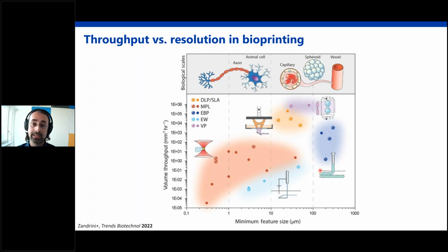And specifically, we developed together with partners in Lausanne a new bioprinting approach that has now been around for a few years since we first published it, which we term volumetric bioprinting. It allows us to have a pretty good resolution in the same range of DLP printing, but a much higher fabrication rate, so you can generate centimeter-scale constructs in a matter of a few seconds.